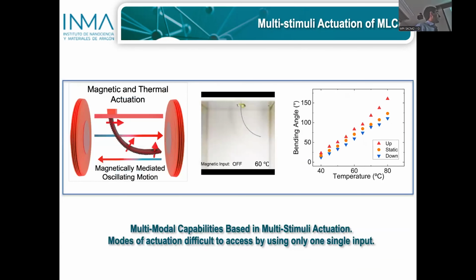And now we can combine these two stimuli. For example, we can heat the sample, generate some bending, and bend the sample to a certain level, and then apply a magnetic field, an oscillating magnetic field. So you can see that we can reach different modes by combining different temperatures and different magnetic fields, and generate these modes of actuation that are difficult to achieve with one single stimulus.